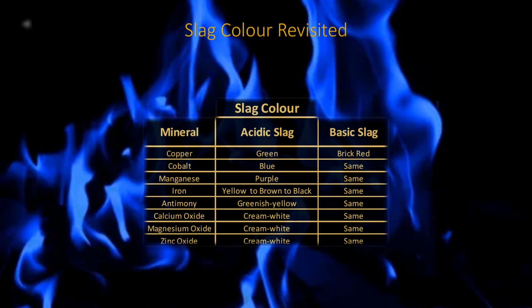Copper will show up green or greenish in an acidic slag, and brick red if your slag is basic. Regardless of whether the slag is basic or acidic, cobalt is blue, manganese shows up as purple, and iron, depending on the concentration, will be yellowish in color to brown to even black. Antimony shows up as greenish yellow, and the rest, well, cream white.